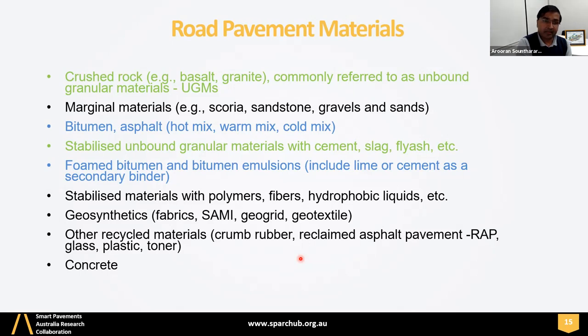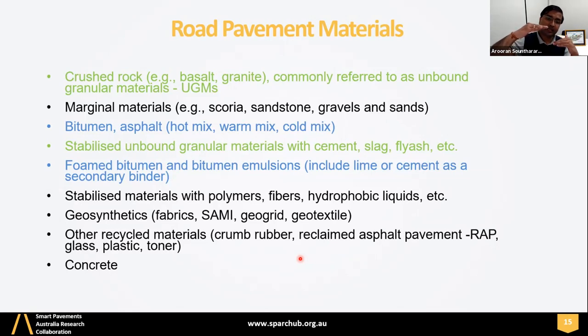SAMI, strain alleviating membrane interlayer, is used to prevent reflective cracking of the layers. In particular, very close to the seal, SAMI is used if the bottom layer is cement-treated base, because cement-treated base can have shrinkage cracking. Therefore, they normally place SAMI such that the crack coming from the CTB, the cement-treated base, is not reflected on the surface of the pavement, because SAMI attenuates the strain or the stress coming through these cracks.